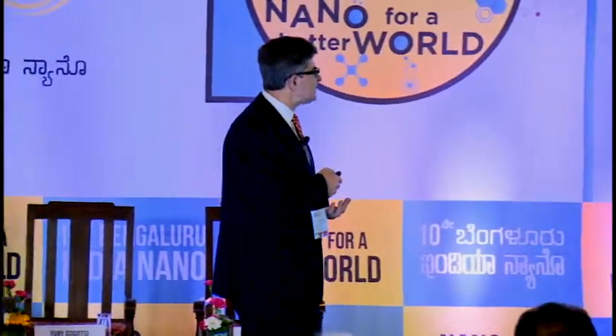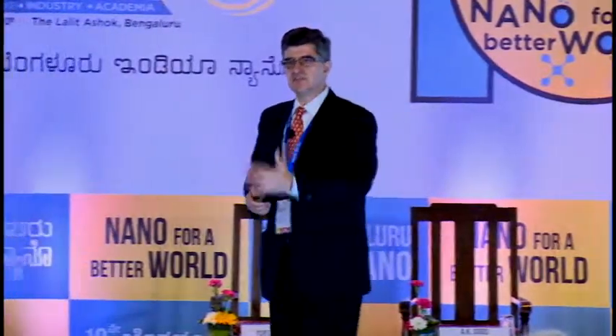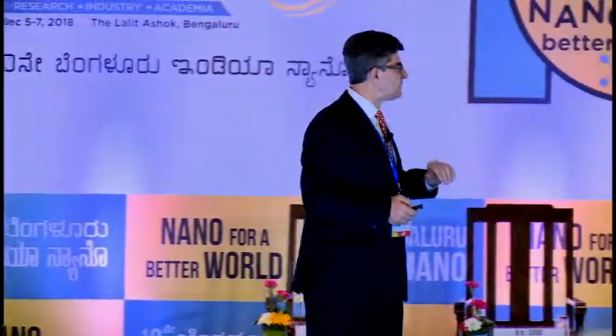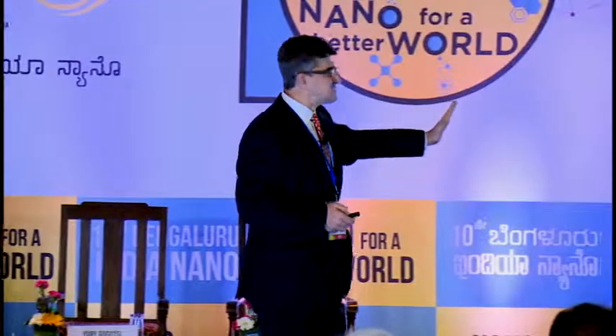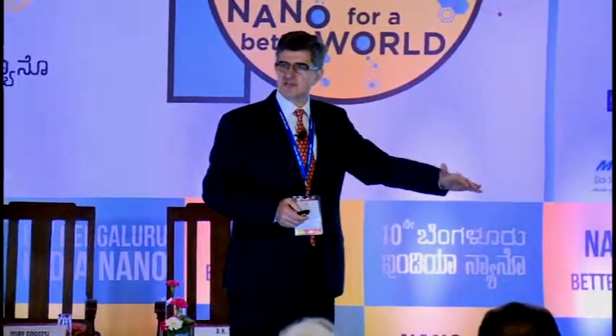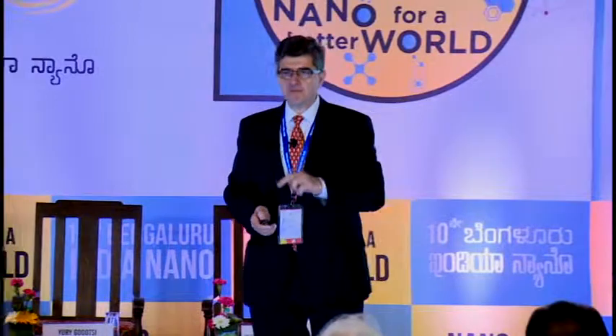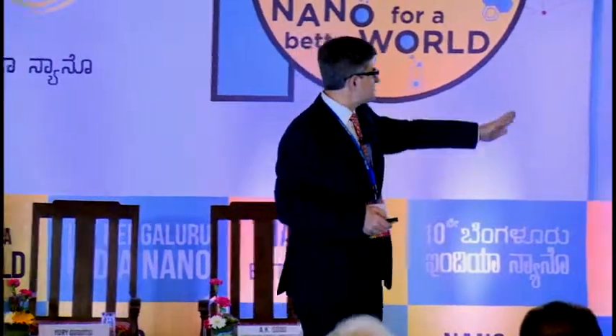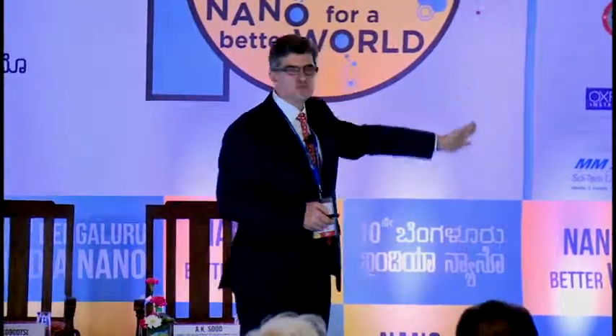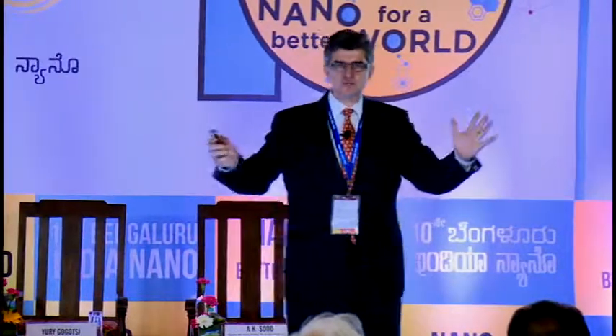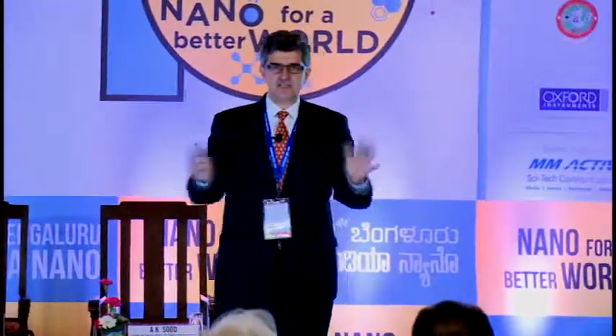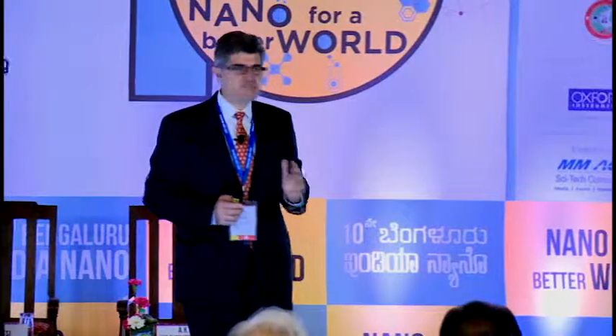And we know the mechanism, because what we always do is build all the applications based on fundamental study. In the case of propylene carbonate, there is a complete desolvation of ions. And lithium ions go between the layers of MXene with no solvent molecules. And it has two advantages. First, it's possible to pack more ions. But second, as you can see from in situ X-ray diffraction, there is no change in the lattice spacing. So there is no swelling, expansion, and contraction. The lattice parameter stays the same.